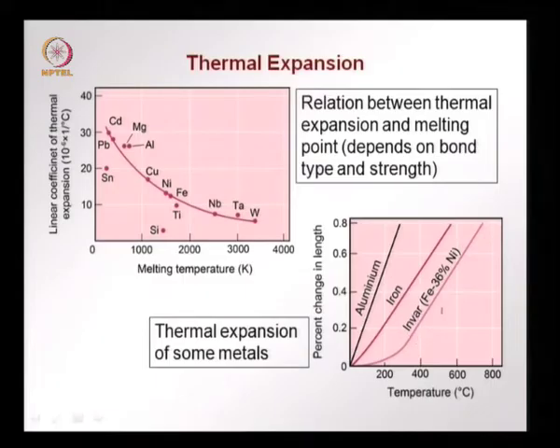Invar, which is iron with 36% nickel, which has a final slope that is parallel to that of iron, but initially we see very little or almost 0 thermal expansion until about 100 degrees, and then slowly increasing, and then finally the behavior is parallel to that of iron. But what is interesting to us is this region.